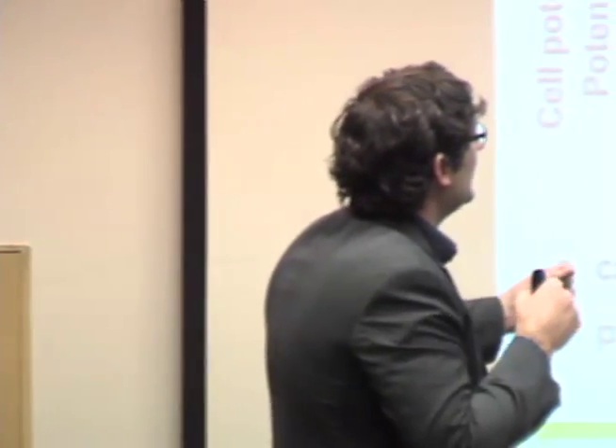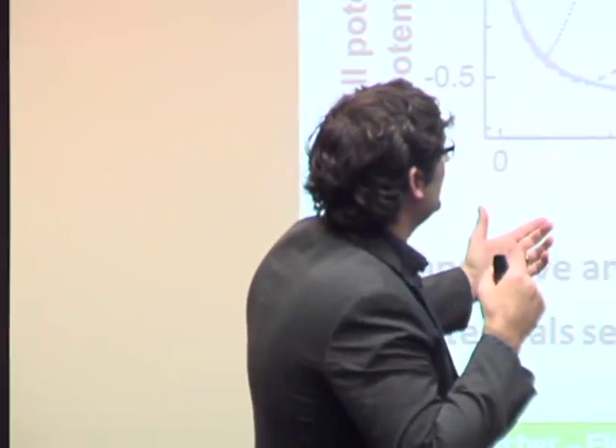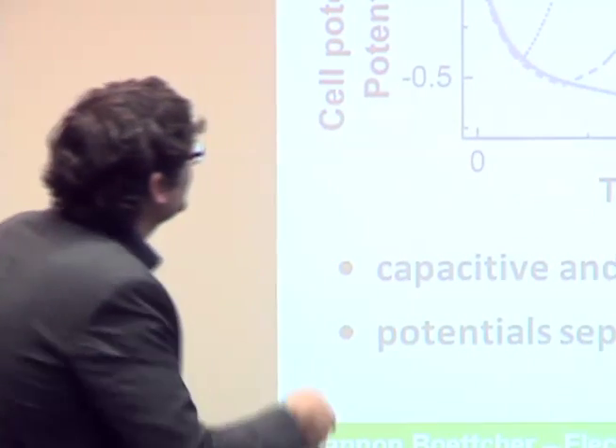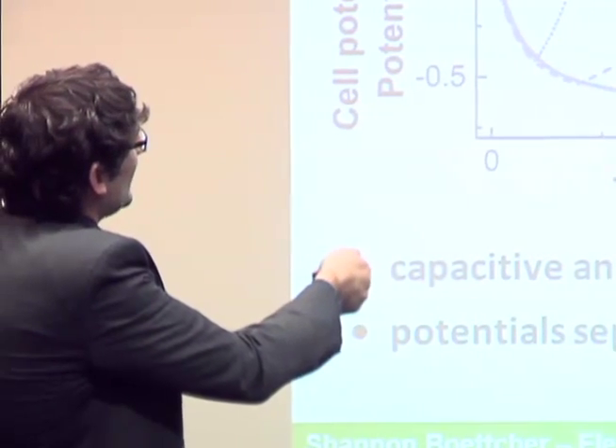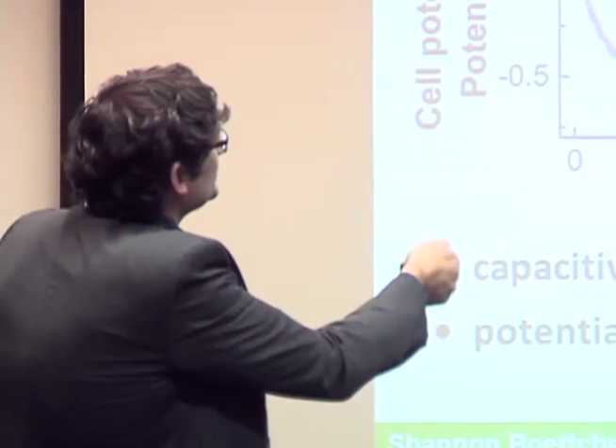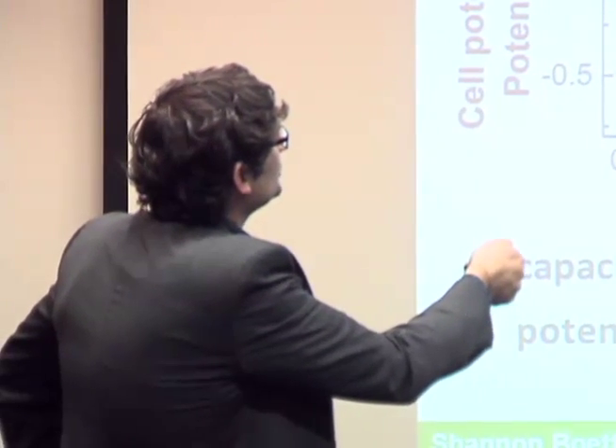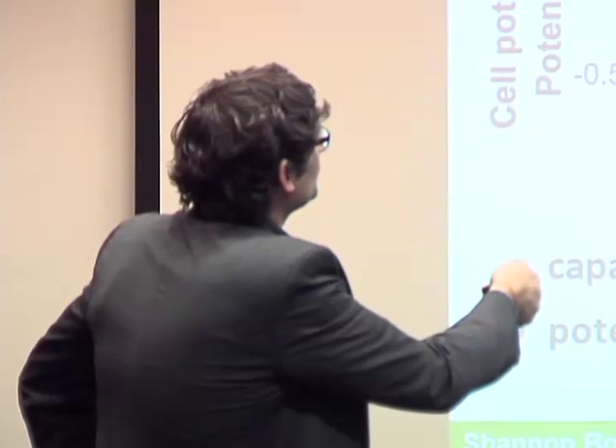You can do a voltammetry experiment. It's very similar, where you sweep the potential of the 2 electrodes and you measure the individual potentials relative to a reference, and you see again the capacitive regime. But once this total cell potential gets sufficiently large, you start driving the reversible Faradaic chemistry. And these potentials are separated by about 1.4 volts, which is about ideal in an aqueous electrolyte.